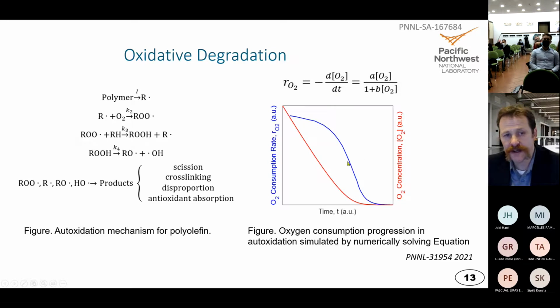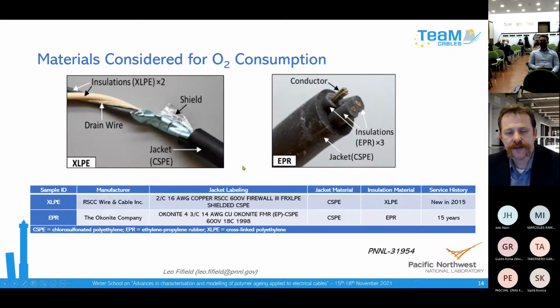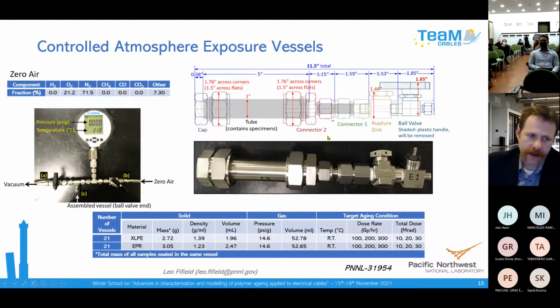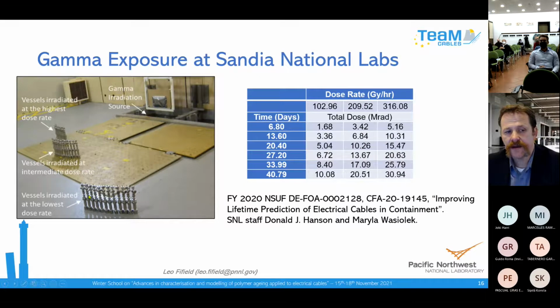This is a very laboratory experiment because you can't measure oxygen consumption in situ in a plant, but you can in the laboratory. So I'll just briefly describe the experiment we did this last year. We looked at a couple of different insulations, XLPE and EPR examples, and these were removed from cables that had a Hypalon or chlorosulfonated polyethylene jacket, but we remove just the insulation, and we loaded insulation samples into a vessel with a known atmosphere. We're able to load it with a known simulated air atmosphere, and then expose the vessels to the stress, and then we can measure the changes in that atmosphere to quantify how much oxygen was consumed.